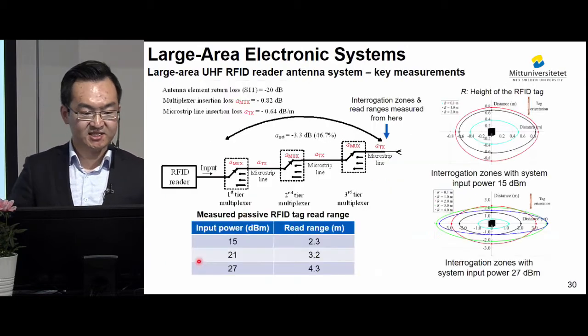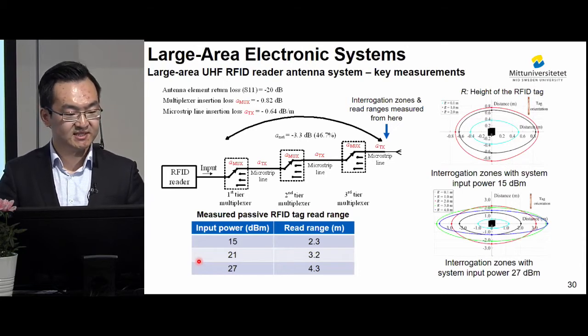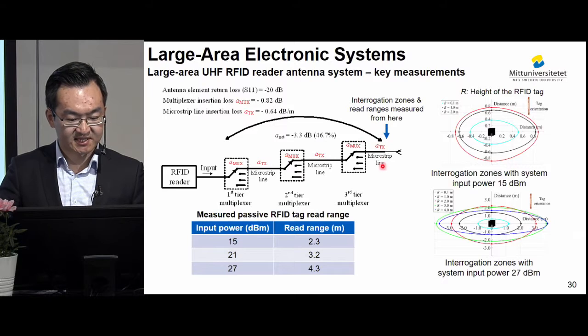The key measurement of this antenna system showed that the antenna elements are well matched to the resonant frequency, and the multiplexer has an insertion loss of 0.82 dB. The microstrip line insertion loss is minus 0.64 dB per meter, which means that the attenuation of the whole network is minus 3.3 dB, which means that the microstrip antenna element here will have 46.7% of the power from the RFID reader.